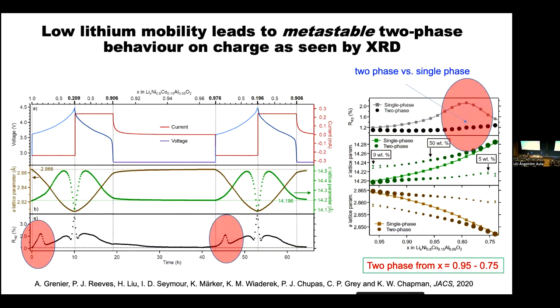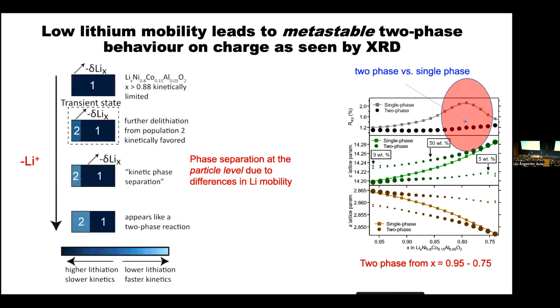So what you're seeing is in a material that has the signature electrochemically of being a solid solution, and that's what it is thermodynamically, it forms a metastable two-phase reaction as seen by X-ray diffraction. So can we just walk through why this happens?